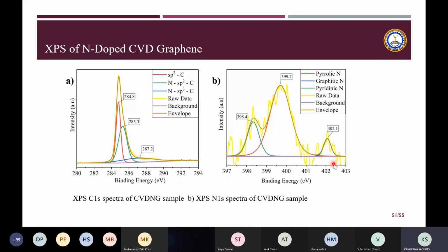And this is the XPS of which one? This is for nitrogen doped CVD graphene. In the nitrogen doped CVD graphene, actually, the nitrogen incorporated into the graphene was not much, and to confirm the presence of nitrogen there, we did the XPS. This is the XPS C1s spectra, and this is the carbon spectra for the CVD-NG, that means the graphene doped with nitrogen, synthesized by CVD. And this is the nitrogen spectra.